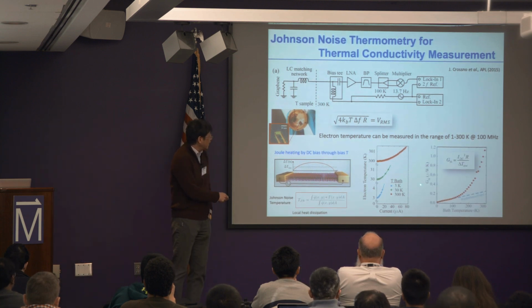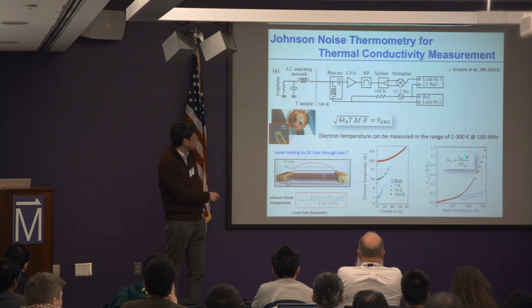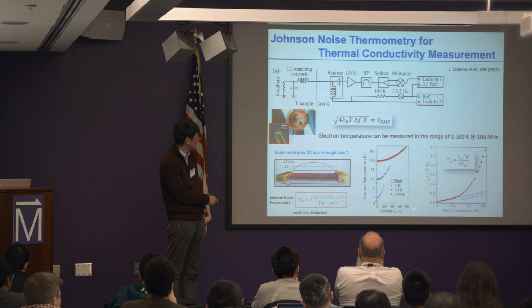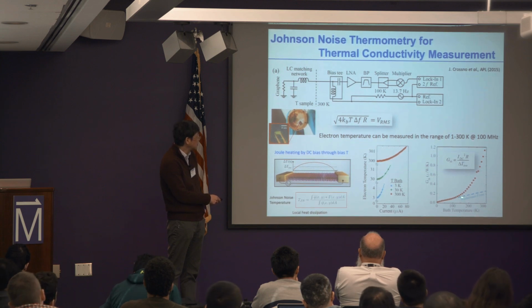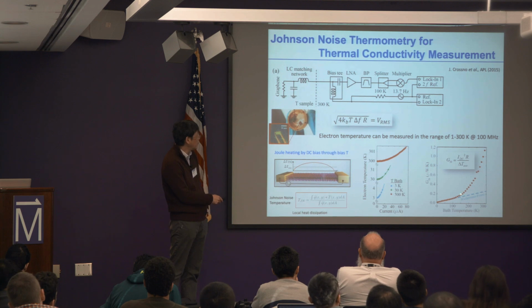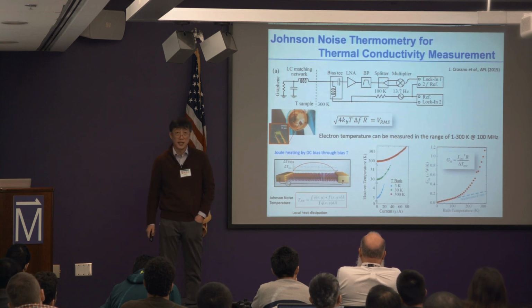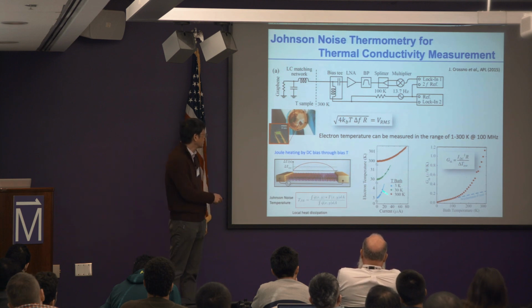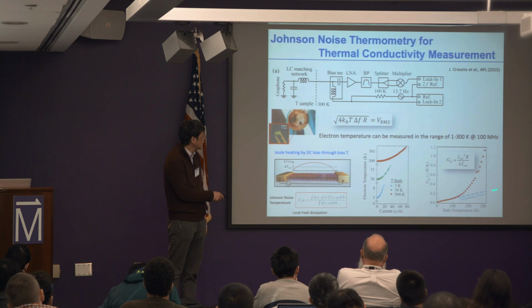All right, so from there we can get the thermal conductance. As a function of bath temperature, we start to see that it increases linearly, and at some point starts to rise much more rapidly. This superlinear behavior is generally seen in typical graphene samples that we measure. And this is linear, the slope.